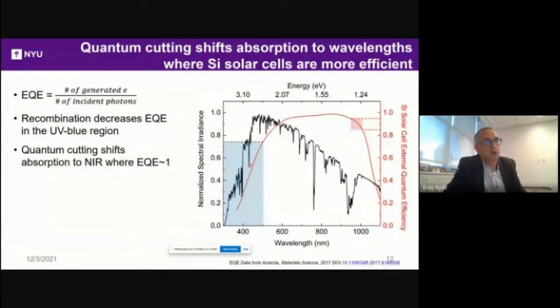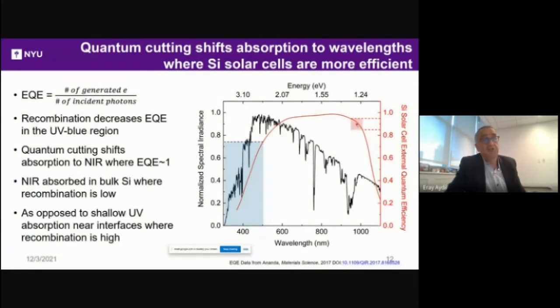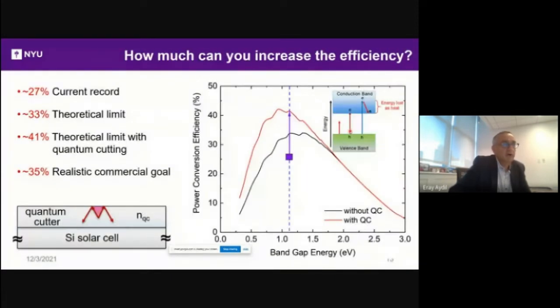So this quantum cutting of taking these photons and putting them here also shifts to regions where the solar cells are more efficient. And this has to do with shallow UV absorption near interfaces where recombination or losses of electrons is high. So you get 2 benefits. One is due to better matching, and also shifting it to where the silicon solar cell is better.